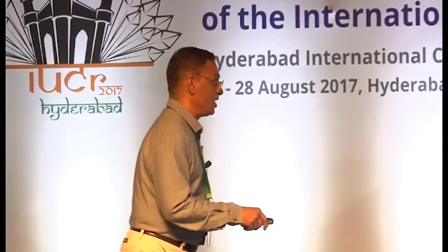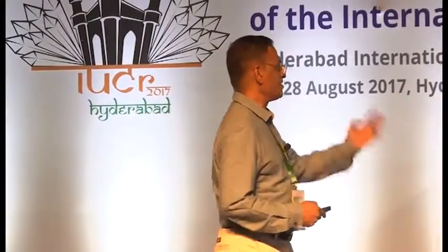But when you see the work of Desiraju, Curtin, and Paul, they have co-crystallized quinone and hydroquinone derivatives. In 1979, they found out that these crystallized in P21 upon C, and they explained this is not the right space group. They said it is due to random distribution of P21 and Pc. Probably, in our case, C2 upon C, it may contain some random distribution of Cc and C2. When you have a mixture of those things, that is what you expect. We thought there should be more explanation to that. In fact, on Monday, Braga gave a nice talk in which he just touched upon this particular aspect. But we thought there's one more way to explain.